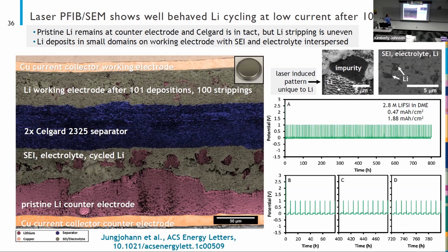And what we would really expect to see is a bunch of pink lithium on the bottom and pink lithium on the top, right? But that's not really what we see. On the working electrode, it's very hard to pick out regions of bulk lithium. So we think that this gray stuff is a mixture of electrolyte, of SEI that forms, and of dead lithium, disconnected lithium, and very small domains of lithium. If the lithium is small enough, we won't see that laser-induced pattern because it's just too small and smaller than the wavelength of it. So we've sort of colored this to explain what's going on.